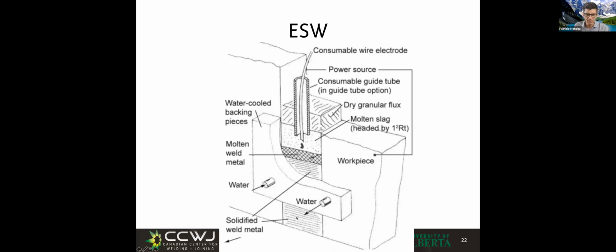So I have solidified weld metal. The shoes that are water cooled move up, typically made of copper, so nothing sticks to it. It moves up and the wire melts. It melts a little bit of the workpiece, that in this case is not clearly shown, but of course you melt a little bit of the base plate and you move up. Electroslag welding. Yeah.